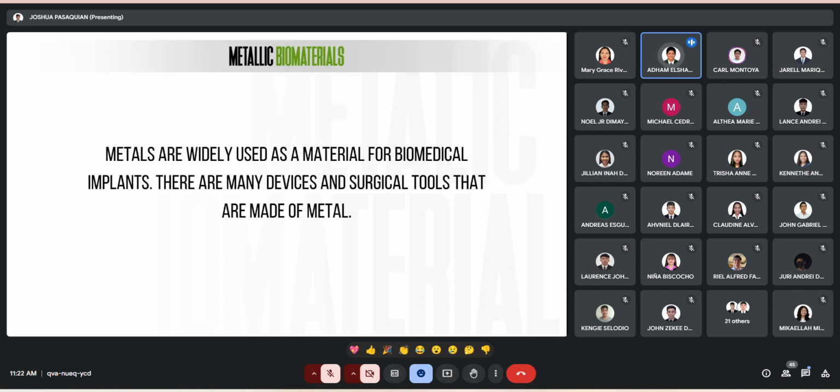The yield and tensile strengths of ASTM F799 alloys are 2 times as high as those for cast ASTM F75 alloy. It has excellent strength, high ductility, and corrosion resistance, and is used in devices and more. An application of it is on the next slide.